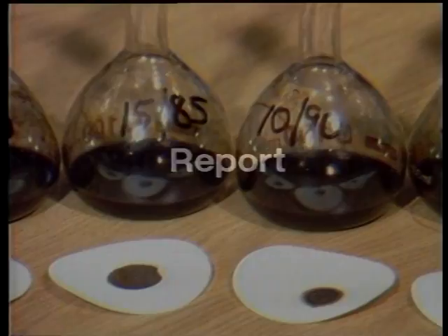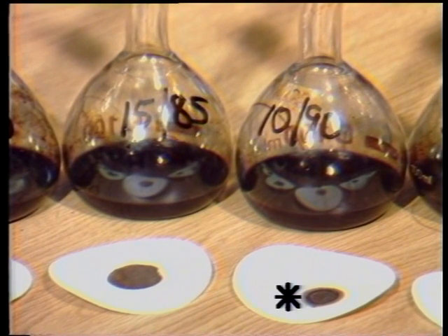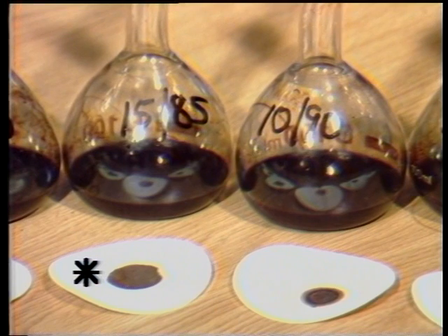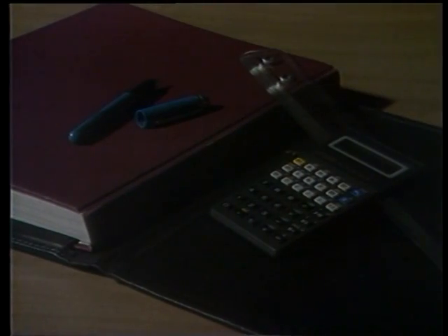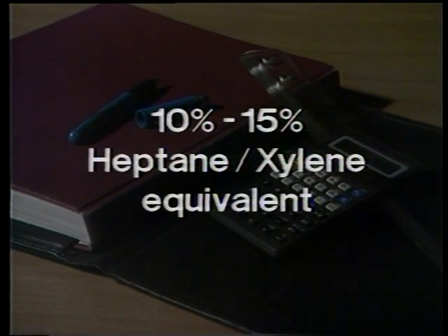Report. Report the result at the percentage xylene that the spot first appears. Also note the next highest concentration of xylene, where the spot did not appear. This example would be noted as 10% to 15% heptane-xylene equivalent.